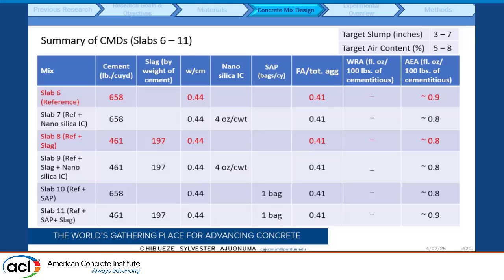And then for the mix, we had six slabs of 8 feet by 8 feet by 10 inches. We had slab number 6, which is the reference slab. We had slab number 7, which is the addition of nanosilica to the reference slab. Then we had slab number 8, where we replaced 30% of the type 1L cement using slag cement, and the grade of slag cement we used was grade 100.